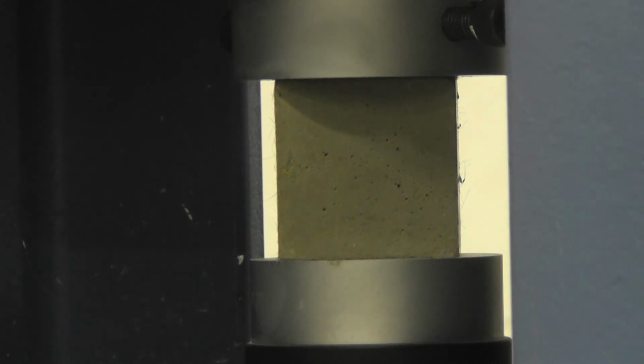And there is also a difference between the strength that you get from a small cube like this versus the strength that you might get from a 6x12 cylinder. We saw in fracture mechanics that the strength is inversely related to the flaw size, right? As you reduce your specimen size, the size of the flaws also decreases, and that's why the strength of the specimen increases. That's just the fracture mechanics size effect. It's true for all concretes and other materials as well. So the strength that you get from this will be about 15% greater than a 6x12 cylinder.